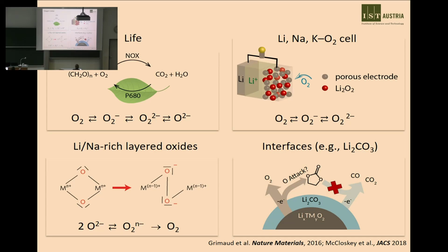And then there's a sort of hidden oxygen electrochemistry. Lithium carbonate is a very common interface component, and typically you want it just as a passivating agent. Let's say this would be your cathode material, and it will be covered by a very thin layer, nanometers thin, of a carbonate layer.